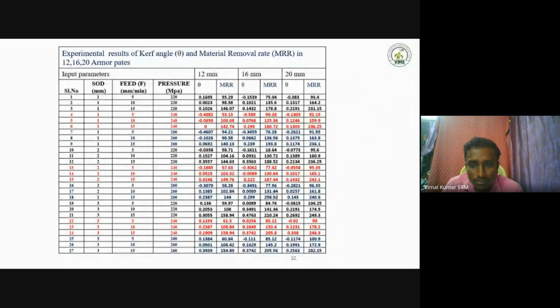Here, for the 16 mm thickness plate, the 19th reading, SOD3, feed rate is 5 mm per minute, 220 megapascal pressure, is good for the 16 mm plate. But the 20 mm plate also varies in the input parameters. We can see the theta value, the theta and kerf angle. Here we can see 0.02. This one is also very good. We can achieve a straight cut. Only a minimum level of tolerance is achieved here as compared to other readings.